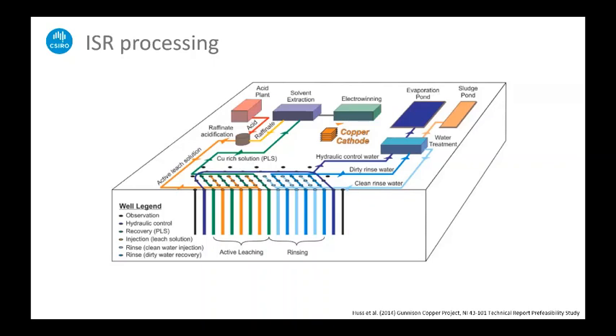This is a diagram from the Gunnison Copper Project Technical Report Pre-Feasibility Study, and it shows essentially how an in-situ operation would work. So you've got active leach solution that flows into these injection holes in orange, and the green lines represent the copper-rich pregnant leach solution in this case, which is pumped back out from underground to the surface from the extraction boreholes. And there are a variety of different configurations that the well field can be laid out in. Usually you have a central extraction borehole and a number of surrounding injection boreholes, and often more fluid is extracted than injected. So there's a continuous drawing in of fluid towards the extraction borehole, and that minimizes flow to peripheries outside the region of interest.